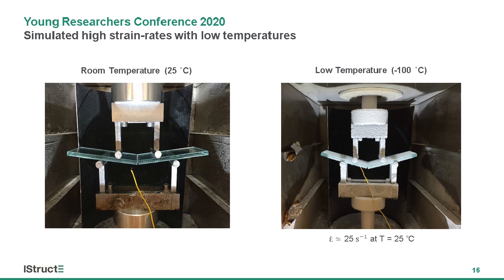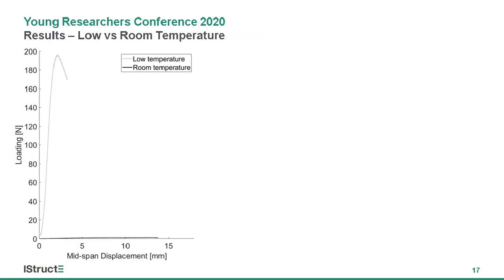The tests were performed on various prefracture patterns, with the images here showing the simplest pattern considered that includes a single crack scored at midspan. A comparison of the load-displacement response recorded from the low and room temperature test indicates a significantly stiffer response at low temperatures.